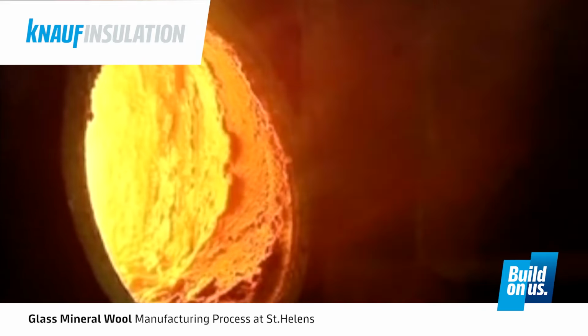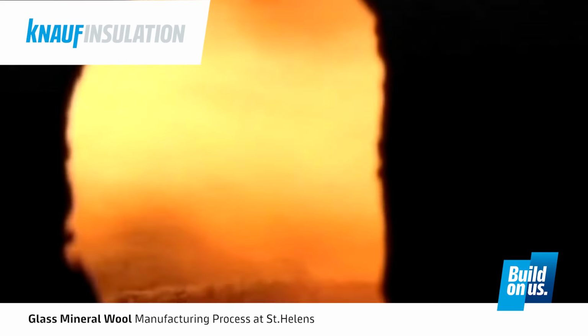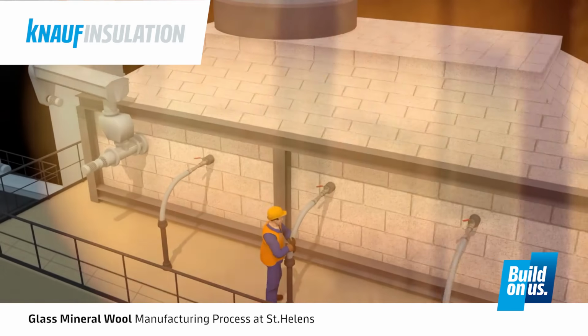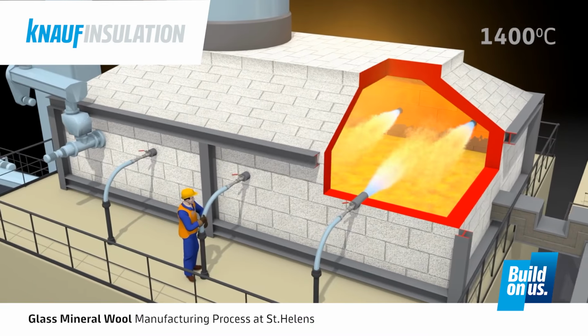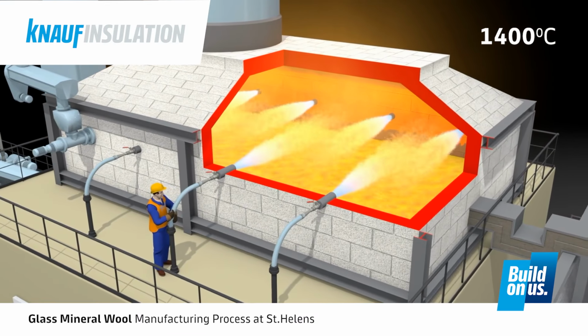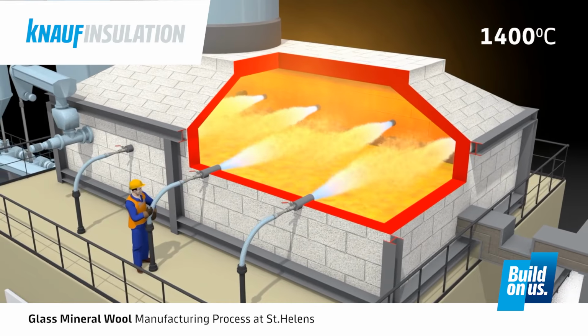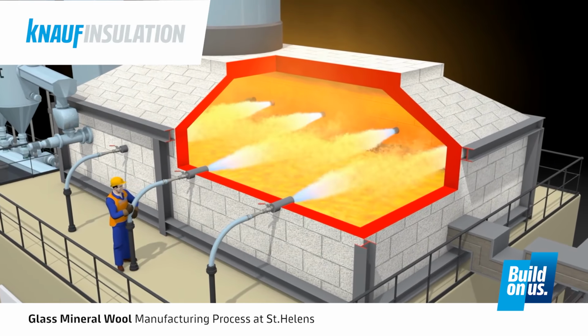Inside the furnace, you'll see a bath of molten glass with some unmelted batch materials floating on the top, with gas-oxygen burner flames above the bed of molten glass, which are providing 70% of the heat. The temperature is around 1400 degrees Celsius in the furnace. You won't see the electrodes as they are below, submerged in the glass.